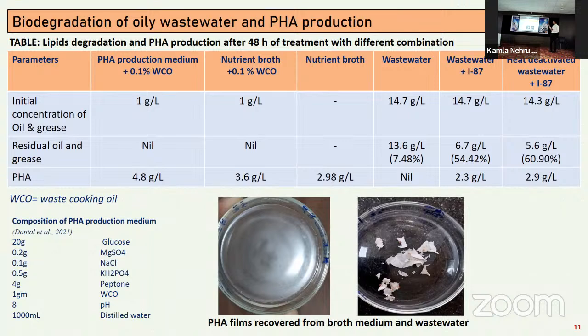the fourth column, in wastewater, if we don't add our culture, then we did not get any PHA production. That is the native microflora which were being used in that treatment plant. They were not able to produce any PHA. But once we add our strain to wastewater, we got up to 2.3 gram per liter and 2.9 gram per liter of PHA in wastewater. And in PHA production medium and nutrient growth, it was even higher, up to 4.8 gram per liter and 3.6 gram per liter. Then we extracted this by solvent extraction and purified it and characterized it further in the next slide.